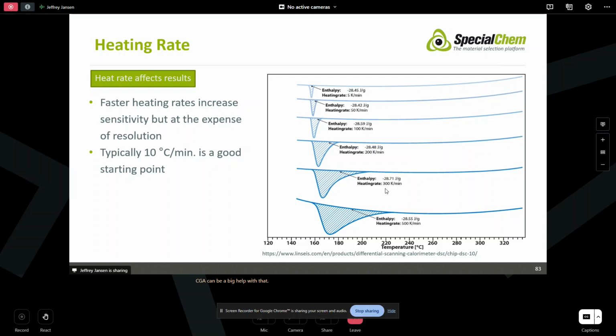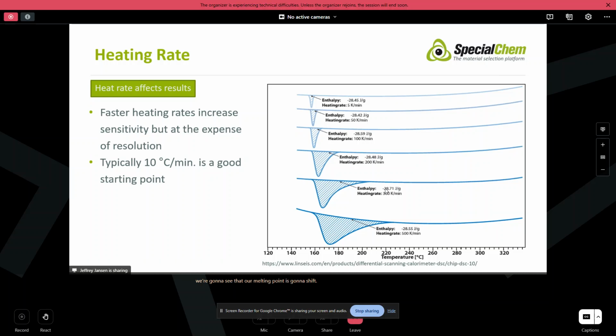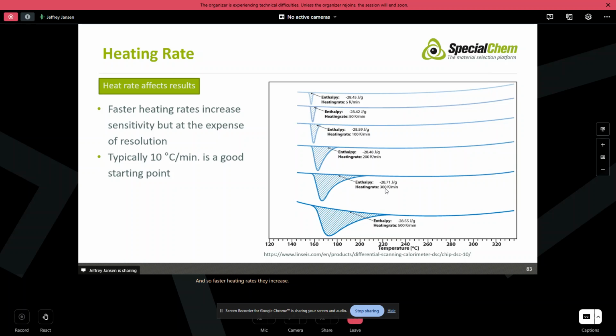Heating rate, again, also is going to affect that. Again, you're looking at sensitivity and resolution, just the same kind of way you were looking at weight. So if we move up as we get faster and faster, we're going to see that our melting point is going to shift. And so faster heating rates increase sensitivity, but they come at the expense of resolution. So typically we find that 10 degrees C per minute is a good place to start. Probably 98% of all our runs are run at 10 degrees C.